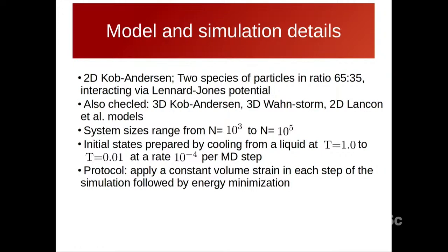So we start with a high density glass prepared in MD, and in each step of the simulation, we strain the simulation box and then minimize the energy. So this is like athermal quasi-static expansion. The strain is the volume strain. We expand the box and minimize the energy. So this is like taking the strain rate to 0 and temperature to 0. So we are in the athermal quasi-static limit.